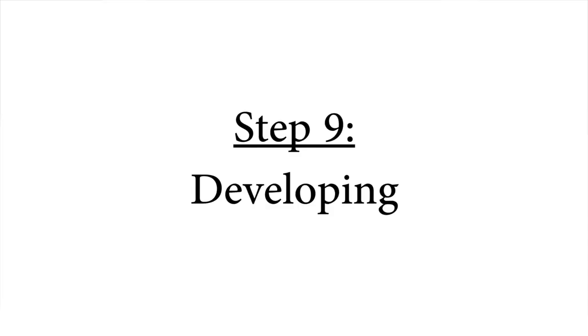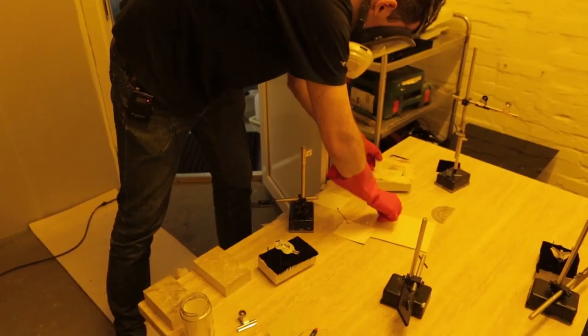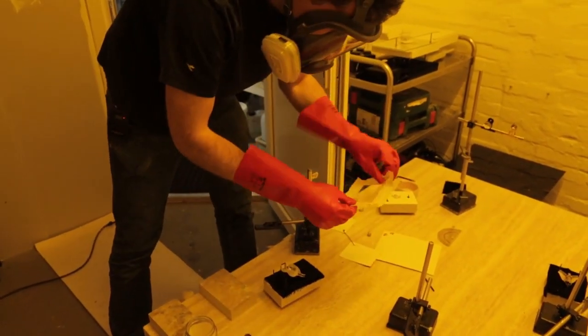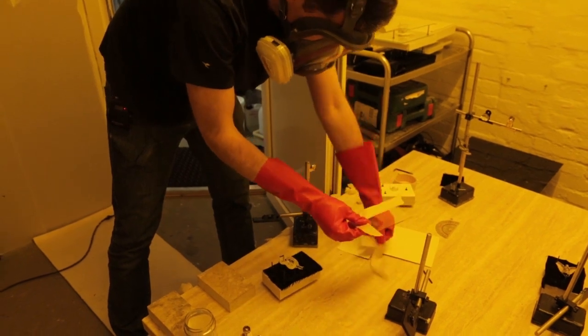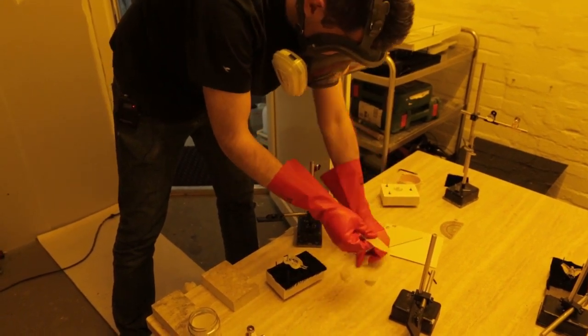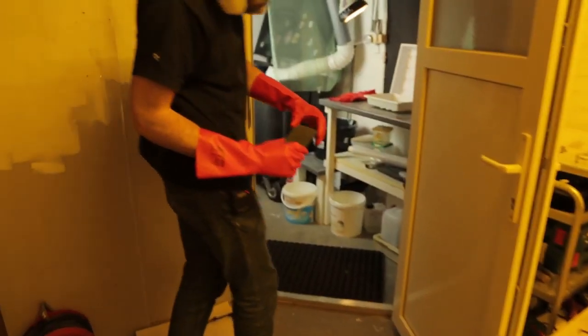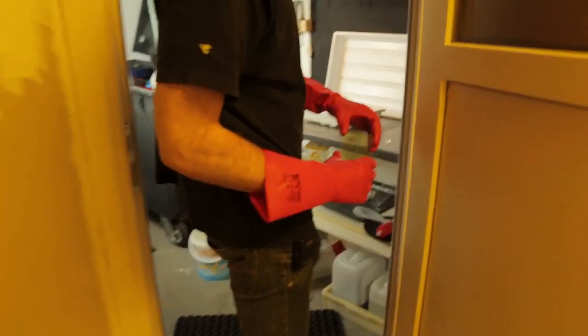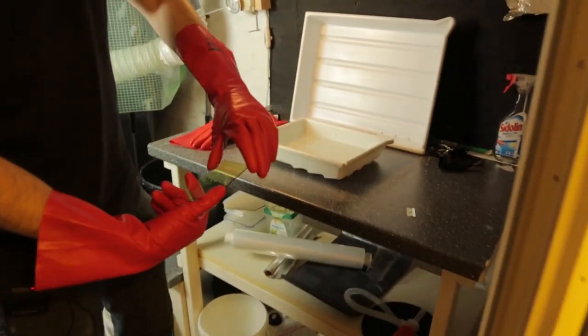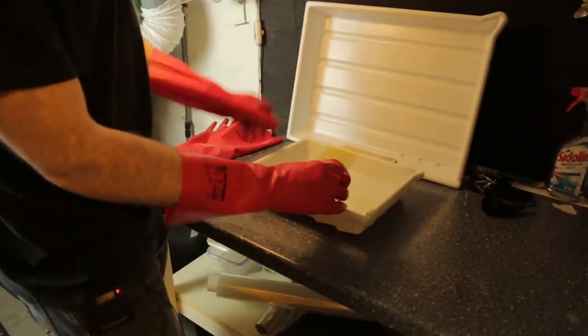Step 9. Developing. 5 minutes after the exposure, I come back into the room. I remove the magnets and take the plate off the setup. And then I carefully remove the masking tape. I walk to the developing area and place the plate into the fixer bath. All the baths have a temperature of 24 degrees.